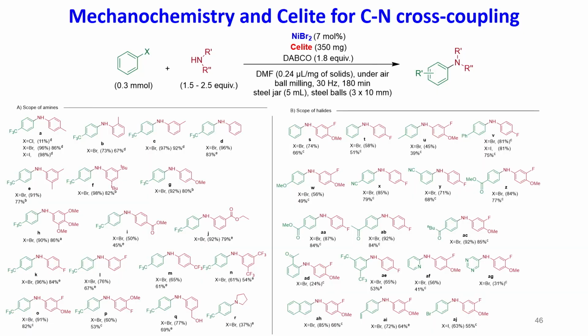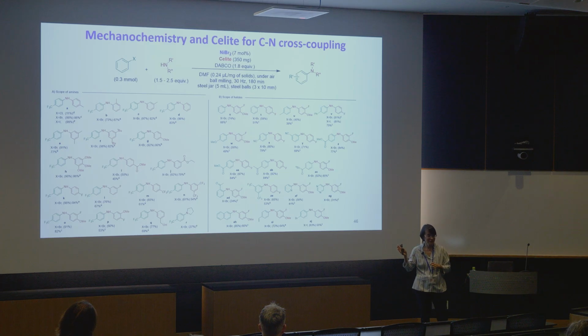So we focused on this particular reaction, and this is the carbon-nitrogen cross-coupling catalyzed by nickel salts. This is a very useful reaction for making amines. And again, Thomas found that it works amazingly well with Celite. But that actually is very strange because nickel bromide that we use here as the catalyst is not really a catalyst, it's a pre-catalyst. So it's a precursor which you first need to reduce to nickel in low oxidation states like nickel 0 or nickel 1 to enter the catalytic cycle. So what is the reductant here? It's definitely not Celite, because if you have something that sedimented millions of years ago, it's very unlikely to be a strong enough reductant to reduce the nickel pre-catalyst.